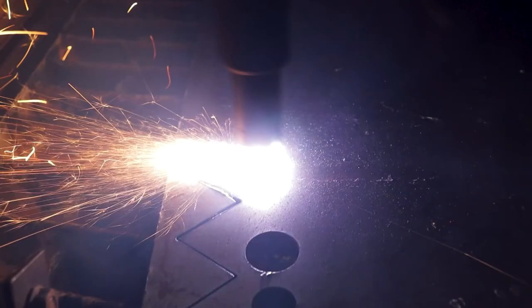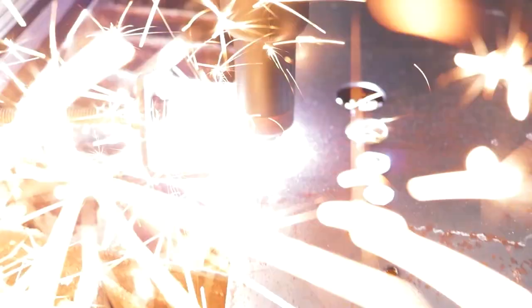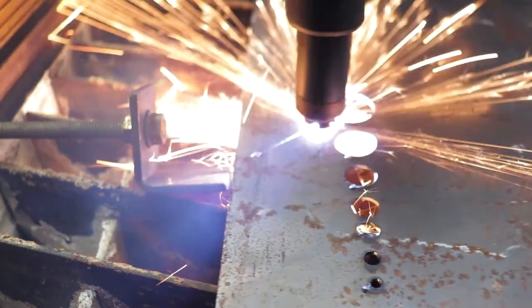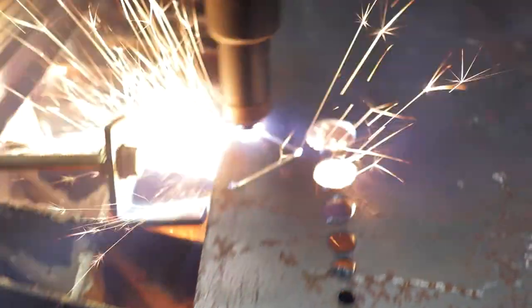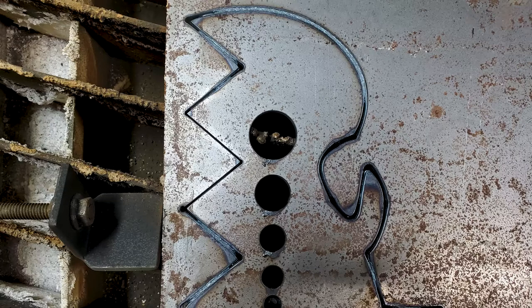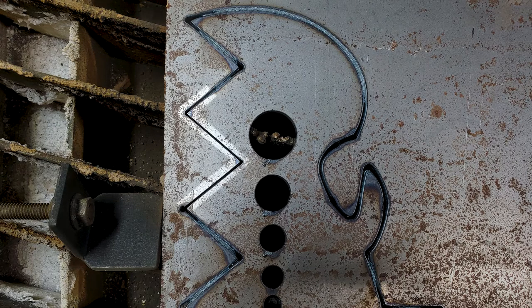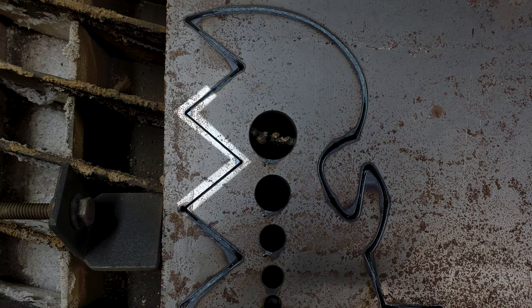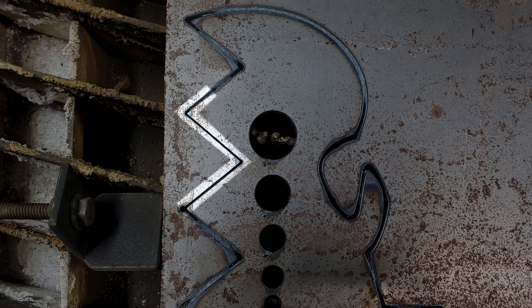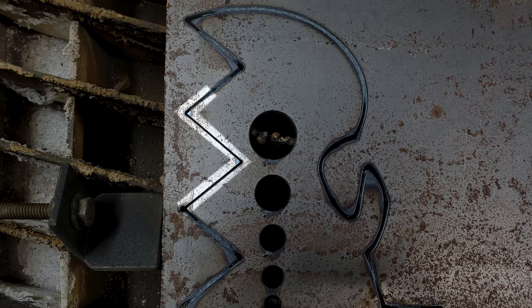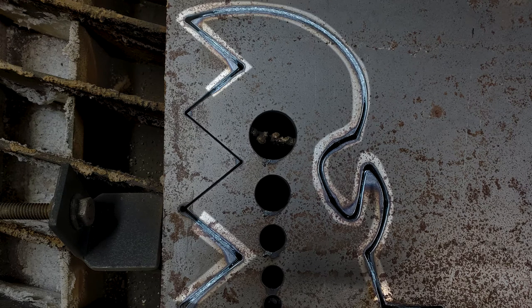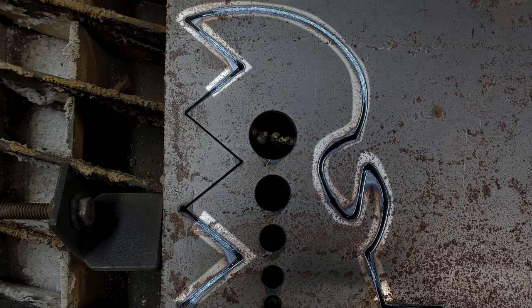Did you catch that? Let me play it again for you in slow motion. The pierce is made. The torch head travels for three inches and then raises up in a shower of sparks. This movement just happens to occur at the three inch mark which is exactly the distance that my torch height control kicks on and you can see the results this causes. For the area with THC off it's almost a perfect cut, and for the area after THC kicks in we don't get good penetration and it doesn't cut all the way through.